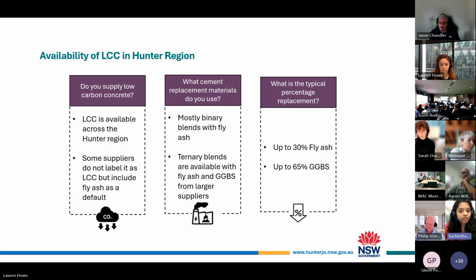And in terms of replacement percentage, I want to highlight the word replacement, that we ask for a cement replacement. It means these mixes have to replace some cement content with SCMs. So it is not simply adding SCMs on top of the cement content that you already have in the mix, because if you do that, it won't be low carbon concrete. It will have a higher embodied carbon compared to concrete without SCMs. So it is important to highlight this is a cement replacement.